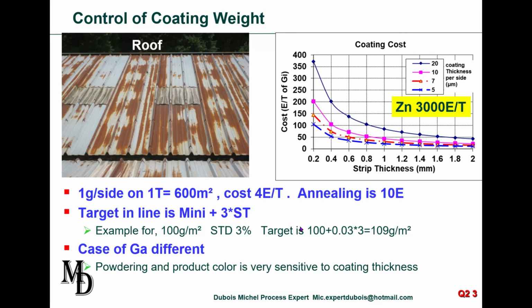So how can you assure that in an industrial process, you always give a coating that's over the minimum value? You have to take the minimum value that is required by the customer, and you have to add 3 standard deviations. Just to give you a very simple calculation, 100 gram is the minimum that you have to fulfill. Standard deviation 3%, and believe me, it's already good. The online target will be 109 gram per square meter. So it's significant. The case of galvanneal is different, because in galvanneal, the coating weight variation impacts the powdering resistance and also the color of the coating.